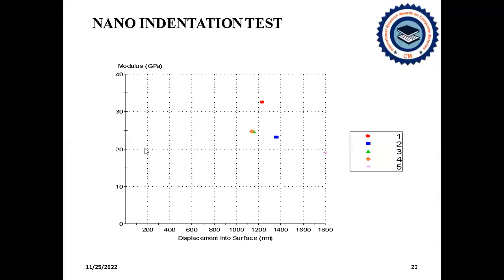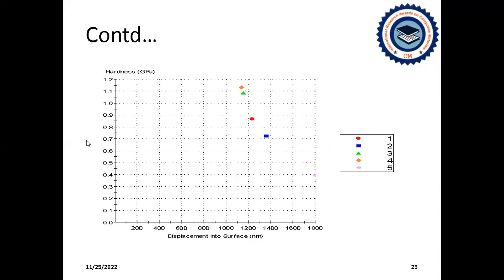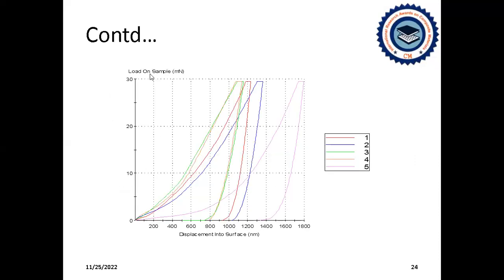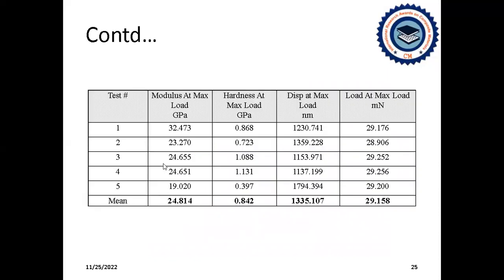This was a result: the Young's modulus versus the displacement into the surface of the specimen. This graph represents the hardness versus displacement curve of the specimen, and this graph represents the load on sample versus displacement. Here we get the values at five different locations. The average modulus of 24.814 gigapascal was found, and hardness of 0.84 gigapascal was found. The mean value from the five locations, as well as the load at maximum, was 30 millinewton.